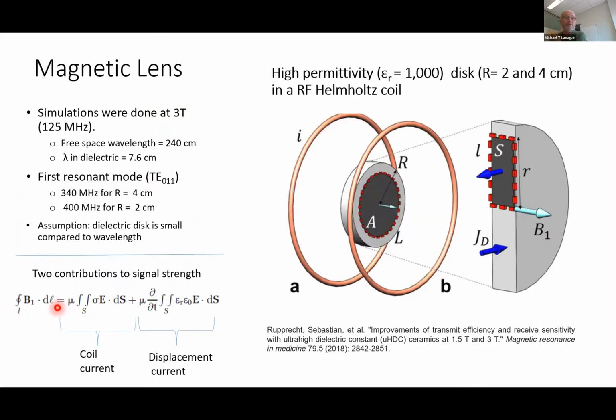And there's actually two contributions. One is the coil current. Coil current generates a magnetic field, but then we can also look at the displacement current, the time varying response of the electric field. And that displacement current has this permittivity concept in it. So this is where the dielectric concept comes in. In this case, the dielectric is just a circle. It's a disk that's located between these two Helmholtz coils.